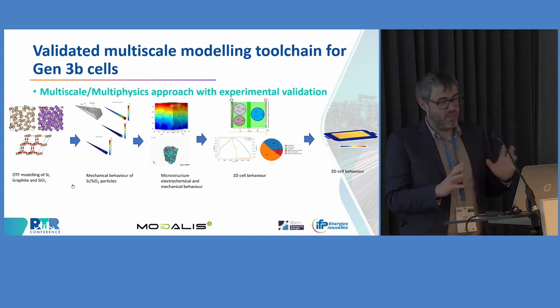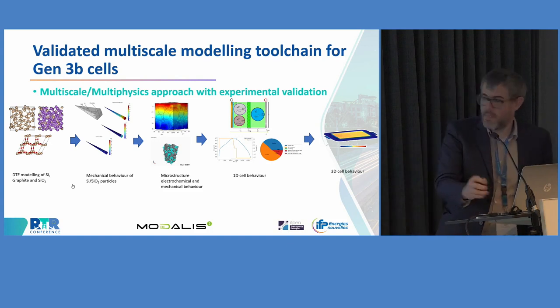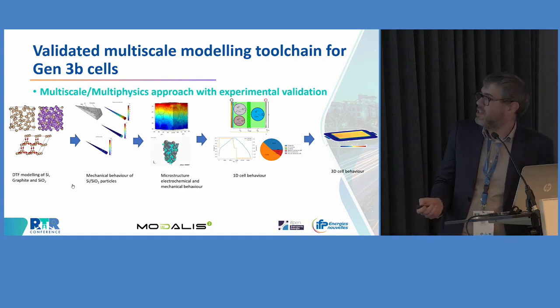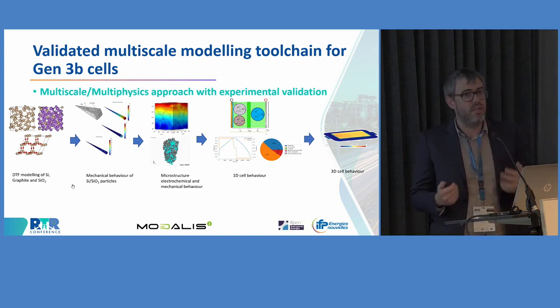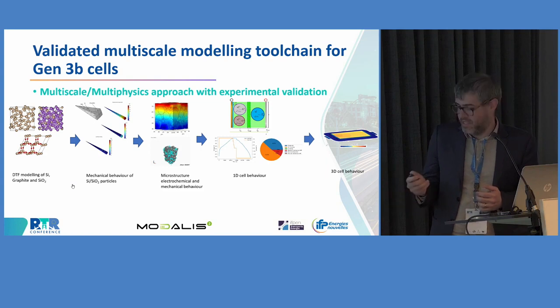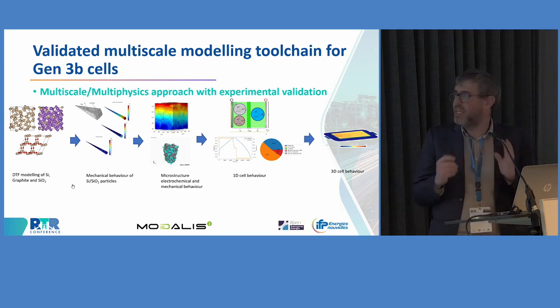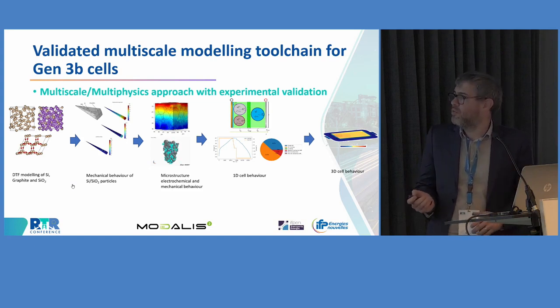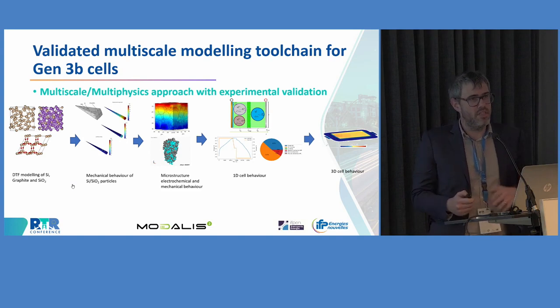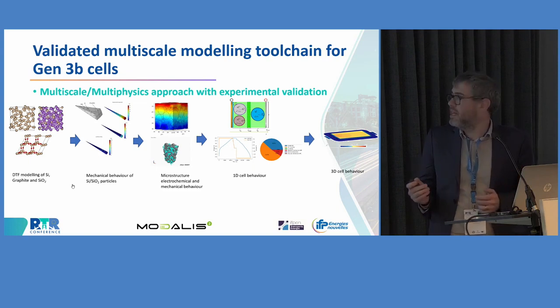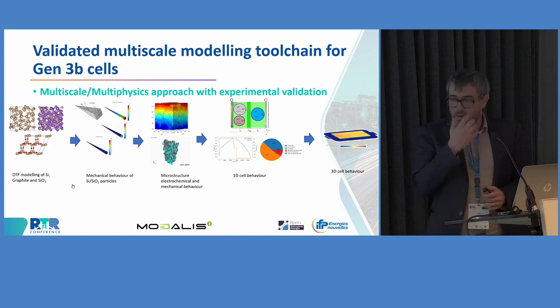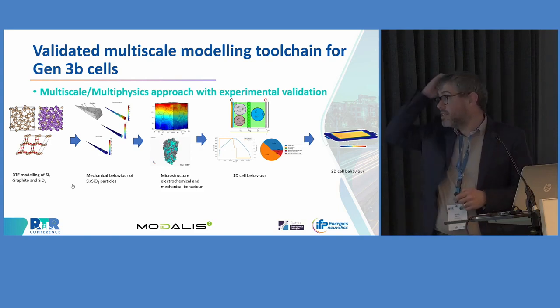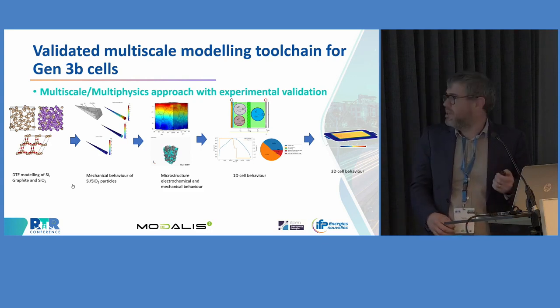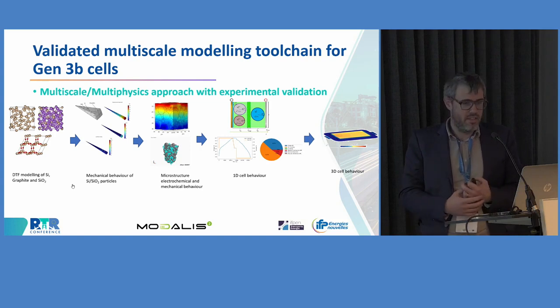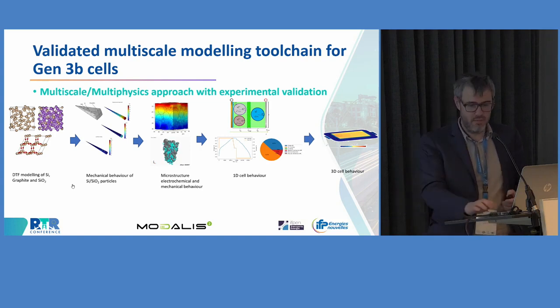These particles, once they were modeled, were put into an electrode scale modeling where we were able to study the mechanical behavior of the electrode. Then this gave us some information on how the electrode works in order to implement it into a full 1D cell behavior model. In this case, we were able to study the aging and safety of the battery, based on the mechanical properties and electrochemical properties of the material. And finally, it was implemented into a 3D model by Siemens in order to evaluate the heterogeneity behavior in the battery and see whether we have some heterogeneity, especially regarding the aging of the battery.